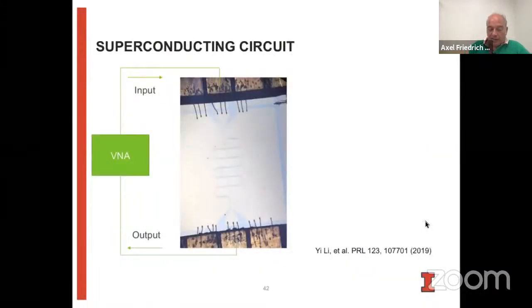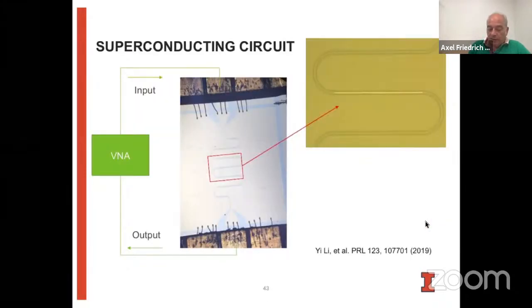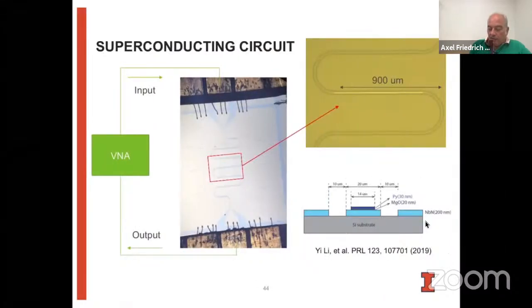So here you see an actual picture of the device that we use, and we measure the microwave transmission using a vector network analyzer. Again, here is the permalloy structure that's in the center of the device. So it's centered on top of the signal line. And you see here a cross-sectional schematic. So we separate the permalloy electrically by having an additional magnesium oxide layer in between. And the permalloy line is laterally a little smaller than the actual signal line of the superconductor.